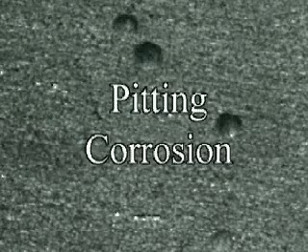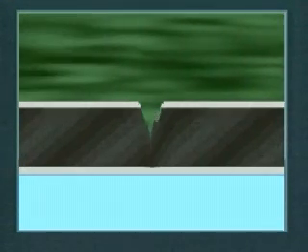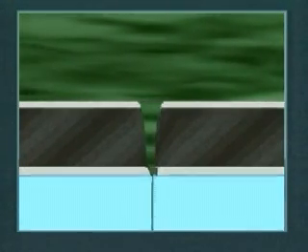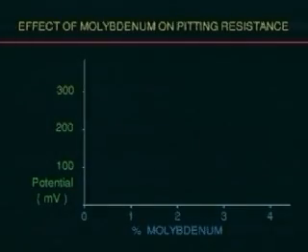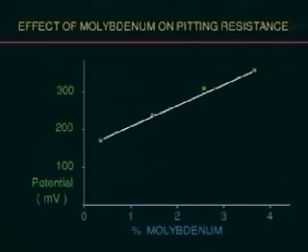The second basic type of corrosion is caused by local breakdown of the passive film. One reason for this is often the presence of chlorides or other halides in the working environment. A small pit forms where the breakdown has occurred, and corrosion continues until the steel is either perforated or the site repassivates, or the oxygen supply to the cathode region is diminished or stopped. This problem can easily be avoided by specifying a suitable higher alloy stainless steel.